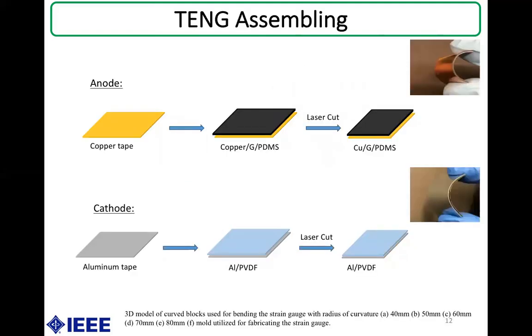With all the materials ready, we move to the nanogenerator assembly. The nanogenerator configuration consists of a cathode layer of PVDF and an anode layer of graphite-PDMS, sandwiched between aluminum and copper electrodes. Aluminum was used as the electrode for the cathode because of its relatively high electronegativity potential, while copper was used for the anode since it has lower potential. The fabricated graphite-PDMS with copper substrate was cut into 1.5 cm × 1 cm pieces by laser cutting.